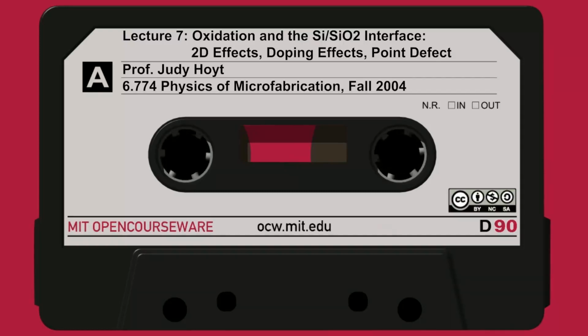What you do, this is the so-called Deal triangle, is anneal the oxide after oxidizing it in an inert ambient at high temperature. The idea is that you try to get some of those silicon interstitials that were stuck there, unoxidized, and give them time to diffuse away from that interface so you can get rid of that fixed charge. And that's exactly what you will find if you run an oxidation program in the furnace.